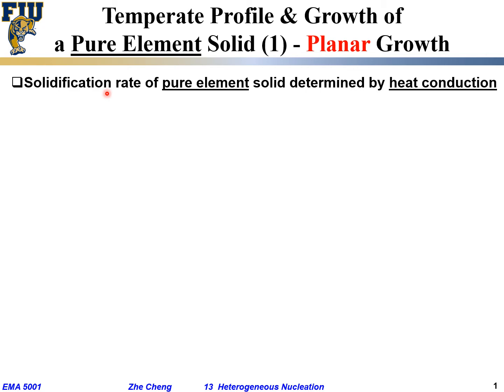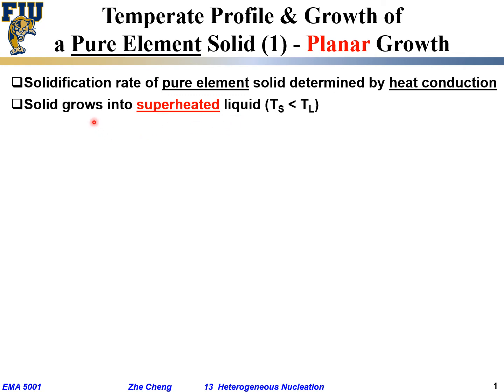That's the rate determining factor for pure element solidification from liquid. Okay, and the first scenario is for solid, the pure element solid grows into a superheated liquid. By saying superheated liquid, we mean the liquid temperature is higher than the solid temperature, or what we show here, TS for solid temperature is lower than liquid temperature. This is what we mean by superheated liquid.